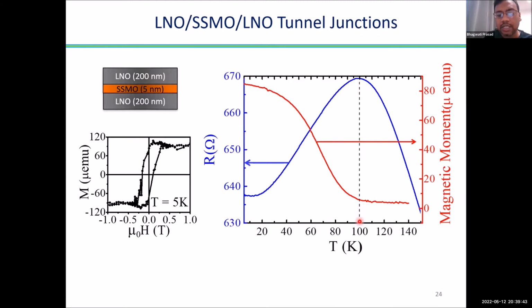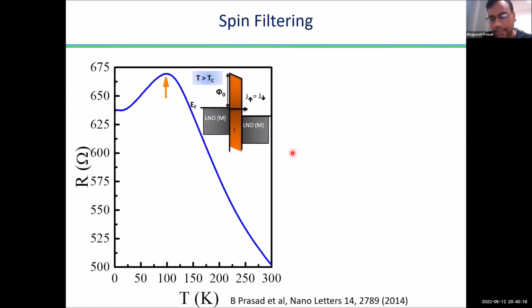The TC is matching with the peak of this R versus T. So it seems that something happening at low temperature is related to the magnetic properties of this barrier, because this is matching with this. In fact, when you measure M versus H at 5 Kelvin, we see nice hysteresis. So this is a magnetic system, and the magnetic properties of this barrier are playing a role here.